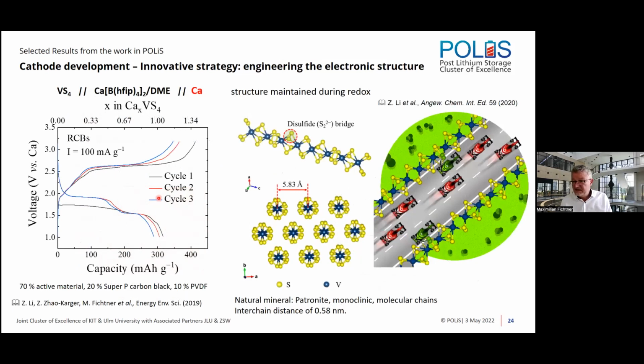That this doesn't only work with magnesium, but also with calcium, is shown here. We have this aforementioned calcium electrolyte with the hexafluoroisopropanoate boron complex. We have calcium metal as an anode. We have VS4 as a cathode. And this is what you get here on the left.